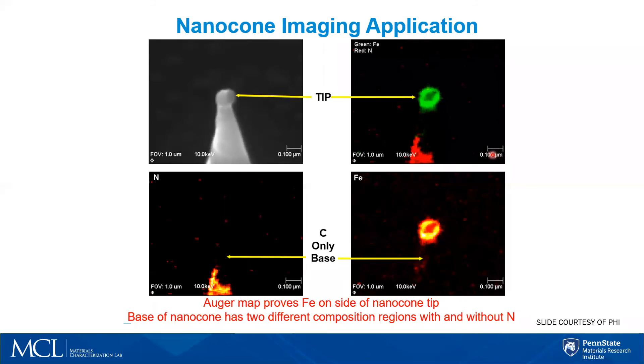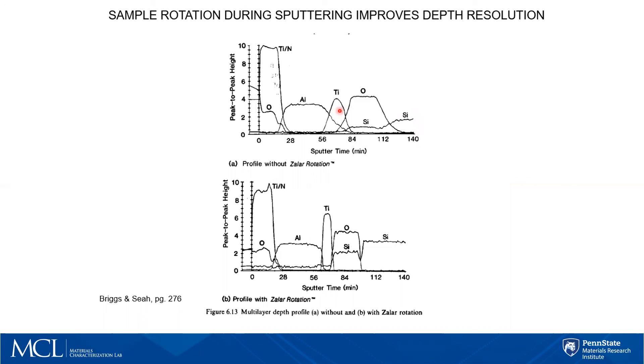The important thing to note here is the spatial resolution — the scale bar is a tenth of a micron. We couldn't do this on the Penn State instrument; our spatial resolution would probably be about a factor of 10 worse. We can depth profile with our instrument. This is an example of a depth profile of a multi-layer film on silicon — a layer of SiO2, titanium metal, aluminum metal, and then titanium nitride. We sputter down through the film and study composition as a function of depth. This depth profile was acquired under two conditions; in the second case the sample was rotated while etching to reduce roughness caused by sputtering, and you can see that depth resolution differs considerably — rotation allows much better definition of the interfaces in the sample.